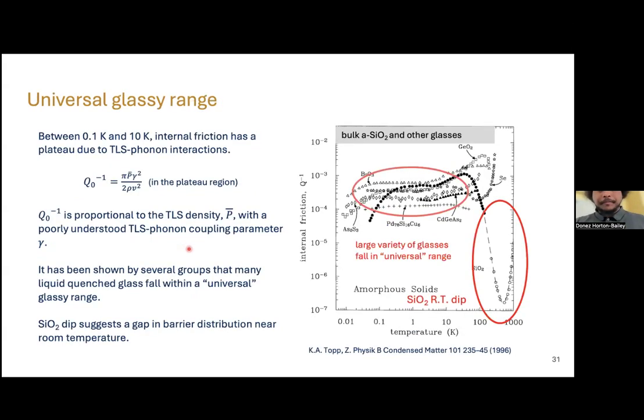And so looking at internal friction of glasses over several decades of research, it turns out that all of these glasses have a typical shape of their curve. There's an internal friction plateau between about 0.1 and about 10 Kelvin. So this is very, very cold temperatures. And it's been seen as kind of a universal glassy range. All of these liquid quench glasses have this plateau, and this plateau falls between specific values, 10 to the minus 4 and 10 to the minus 3.